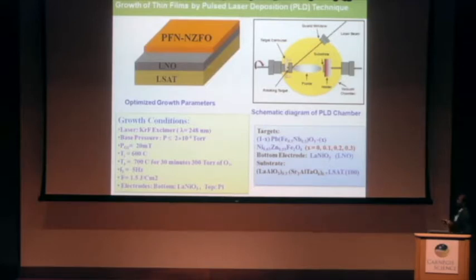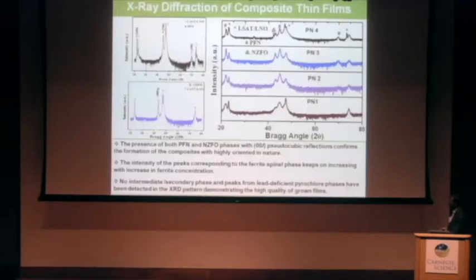We started this synthesis with a single target of PFN and nickel zinc iron oxide, and these are the optimized parameters. We grew at 20 millitorr of oxygen pressure. The substrate temperature was 600 degrees Celsius, and we annealed the sample at around 700 degrees Celsius for 30 minutes at 300 torr of oxygen in order to avoid oxygen vacancies. The laser frequency was 5 Hz, and the fluence was 1.5 joule per centimeter square. The bottom electrode was lanthanum nickelate, and for the electrical characterization, we made the top electrode platinum.